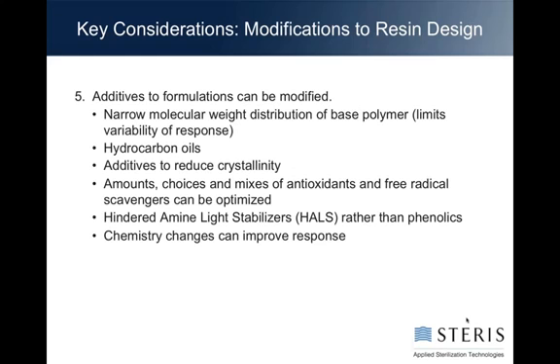Sometimes there's additions of hydrocarbon oils, and they're frequently added as plasticizers. They too become a sink for a lot of this ionization activity. Additives in general will reduce crystallinity. They will keep the product from making these three-dimensional mesh structures in there, which can help control embrittlement. The amounts, the choice, the general mix, the overall recipe of all of these things that can be added will vary. And their choices are made based on the requirements of the product and its use.